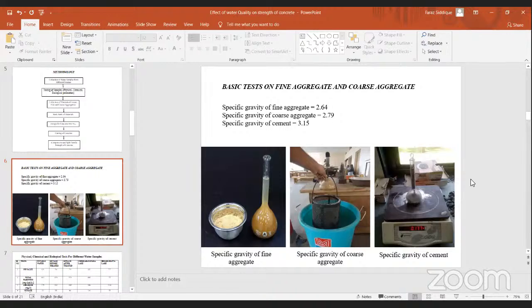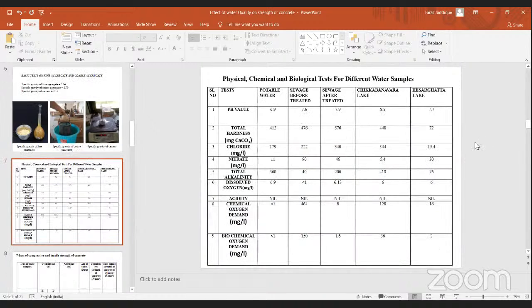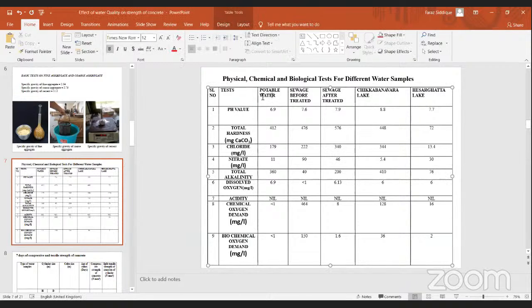These were a few of the tests conducted by us. The specific gravity of fine aggregate we found to be around 2.64, and coarse aggregate around 2.79. With respect to cement, it was 3.15. And these were the biological or environmental tests conducted on the waters. As you can see, we have potable water here. We calculated important parameters such as pH value, total hardness, chloride, nitrate, total alkalinity, dissolved oxygen, acidity, COD and BOD for the different samples of water which we had collected. And these were the results we got.